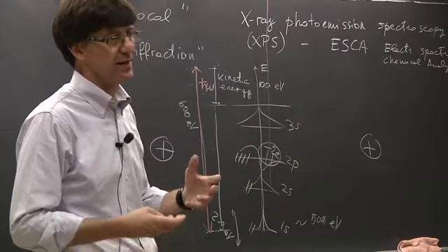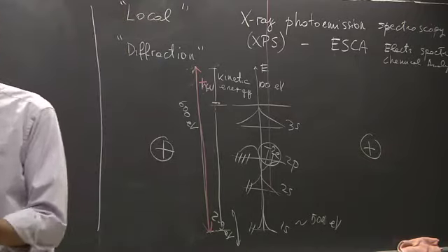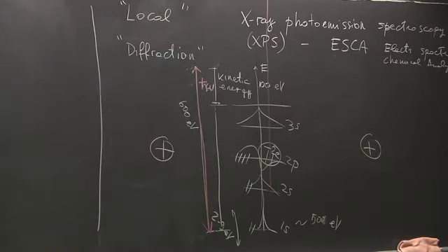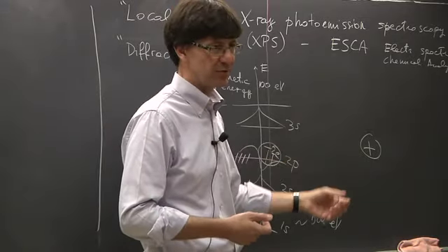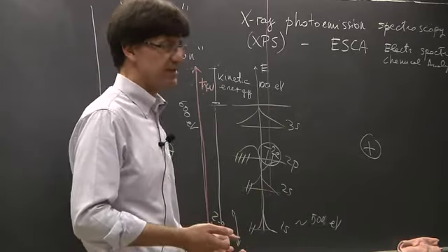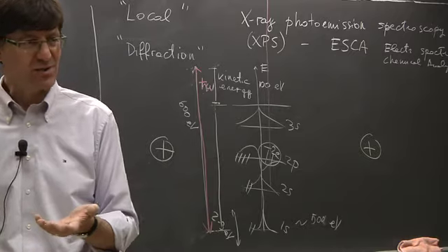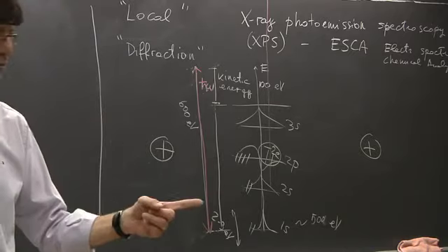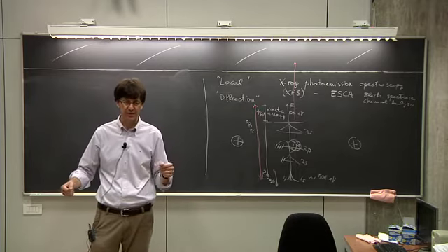If you find a given change in a material that you know has 4 nearest neighbors, and you take another material with 6 nearest neighbors, and you find that the binding energy is different, next time you measure the binding energy, you compare whether it's closer to the 4 one or to the 6 one. And you say, okay, it's closer to the 4, must be 4 nearest neighbors.